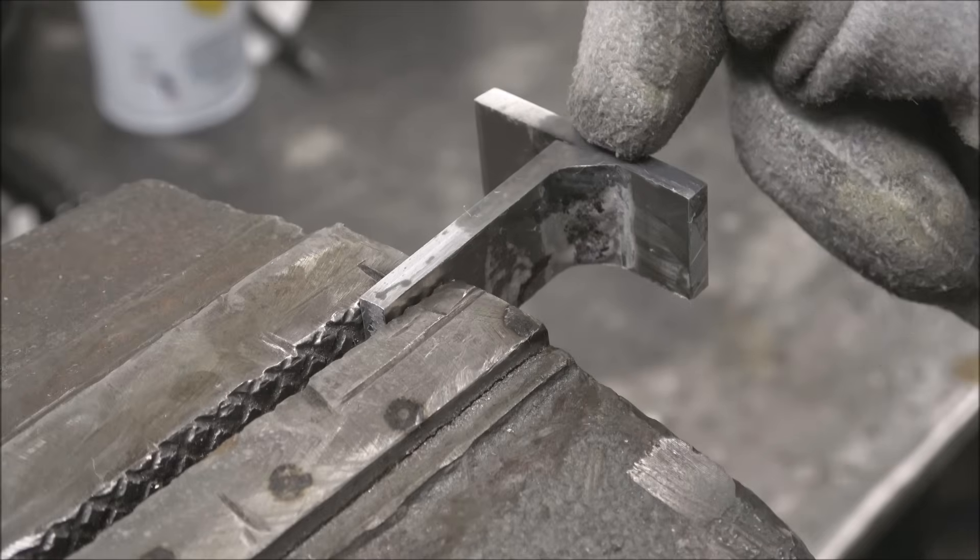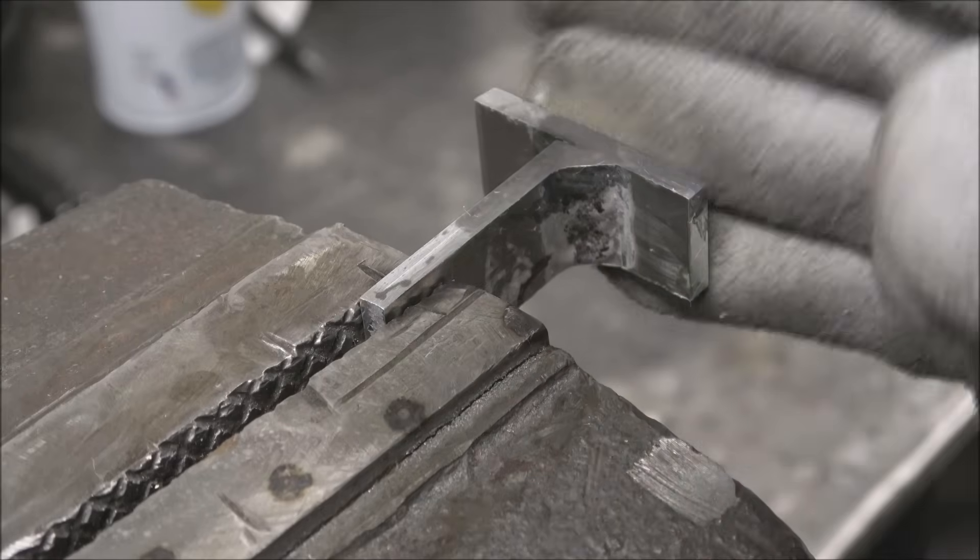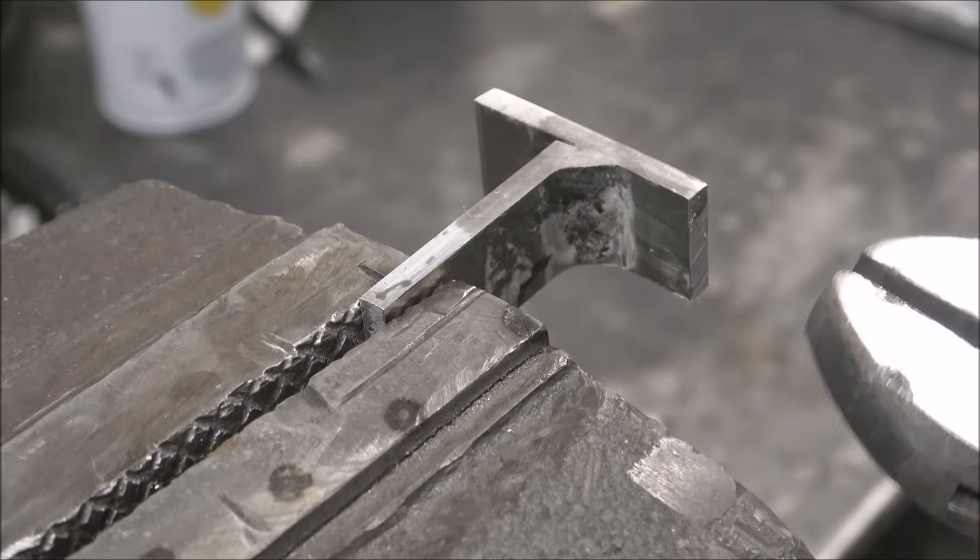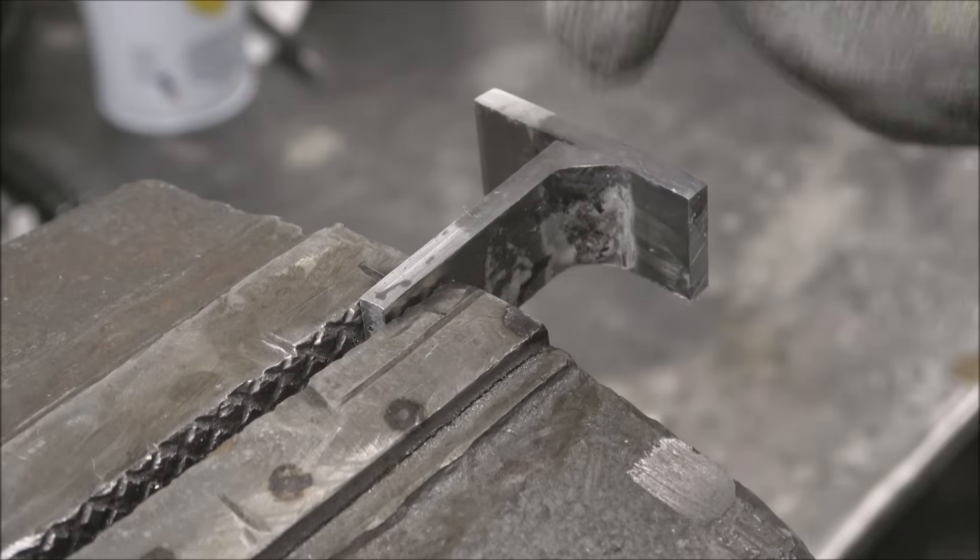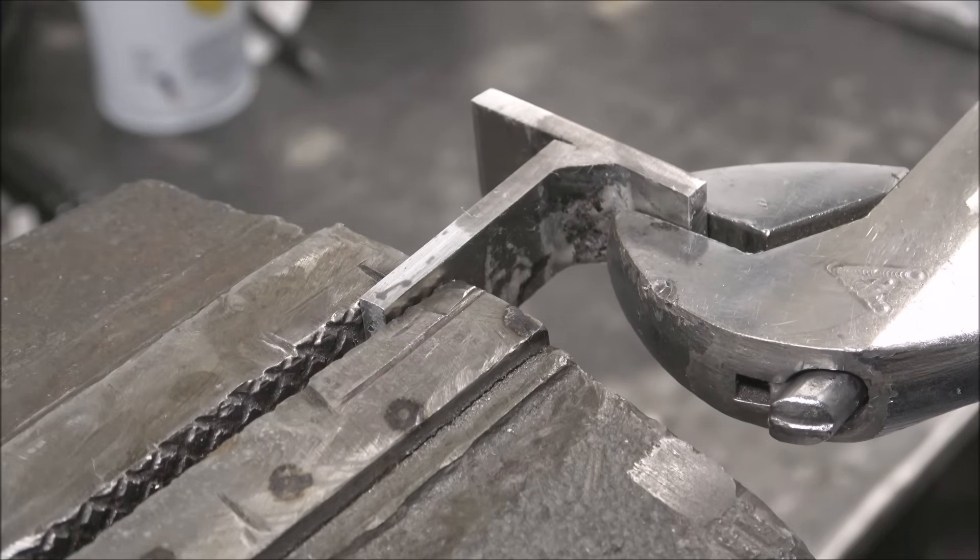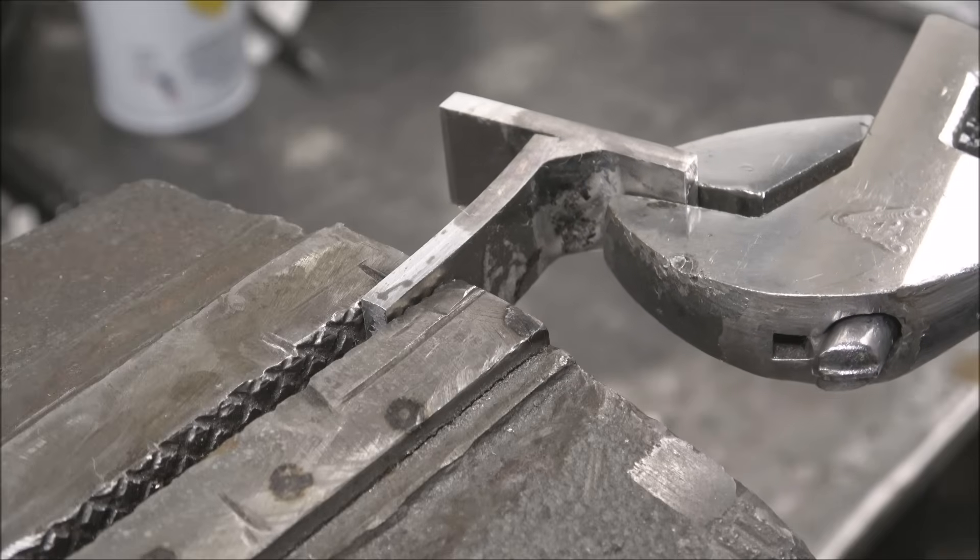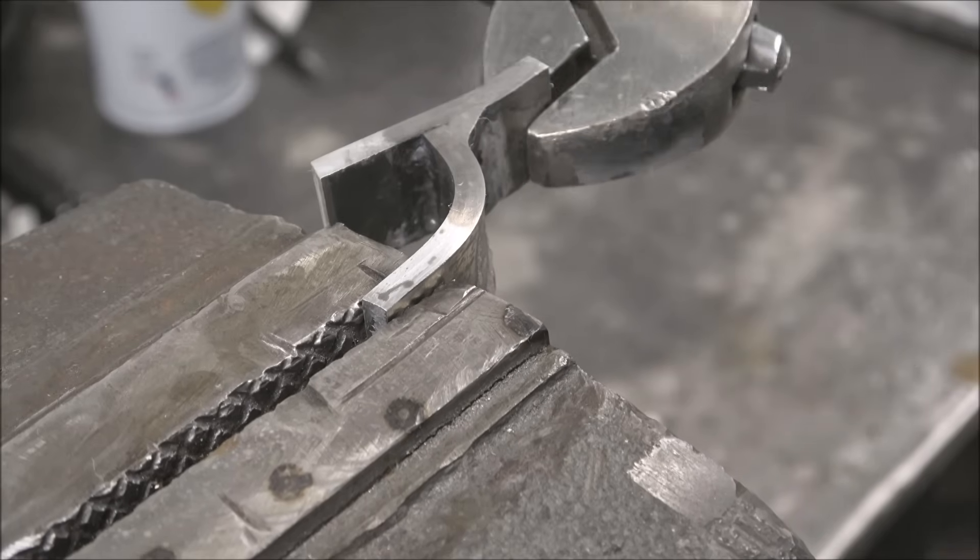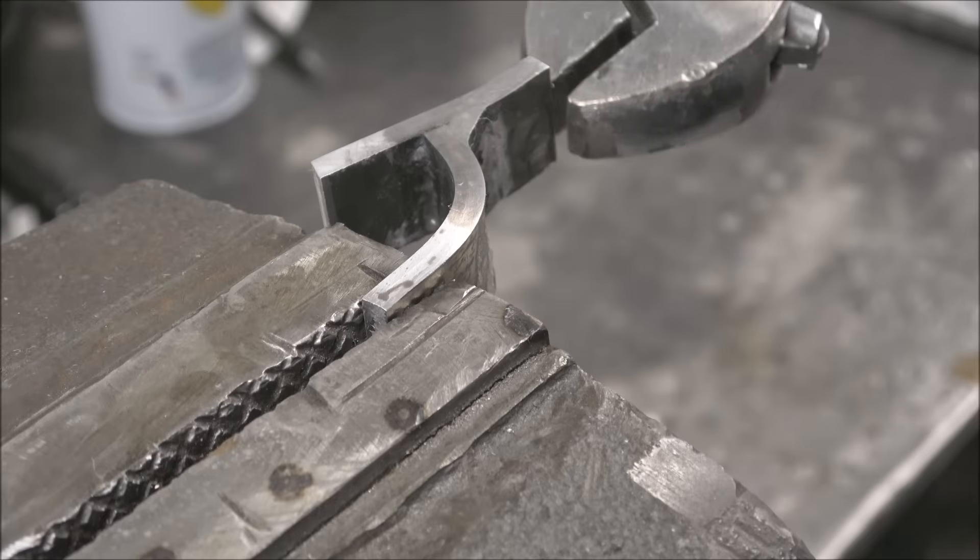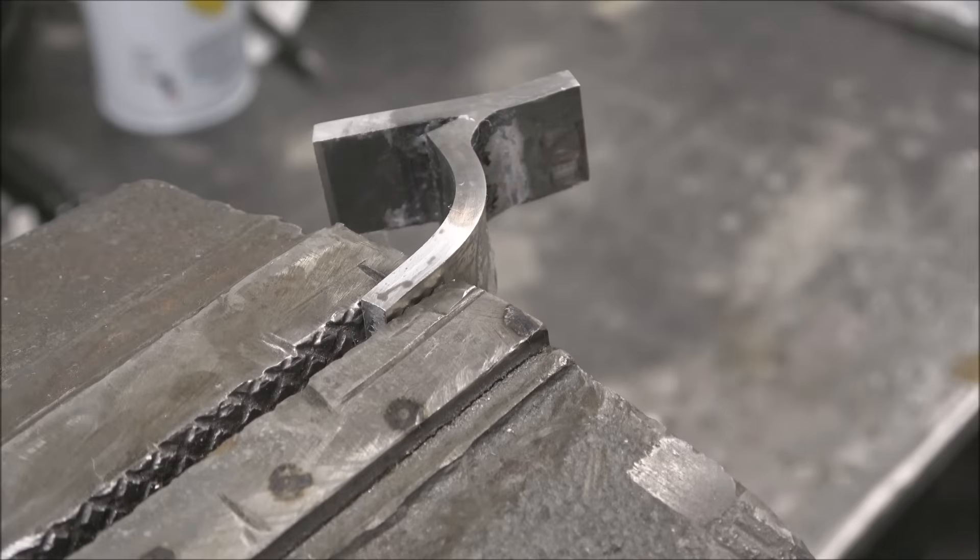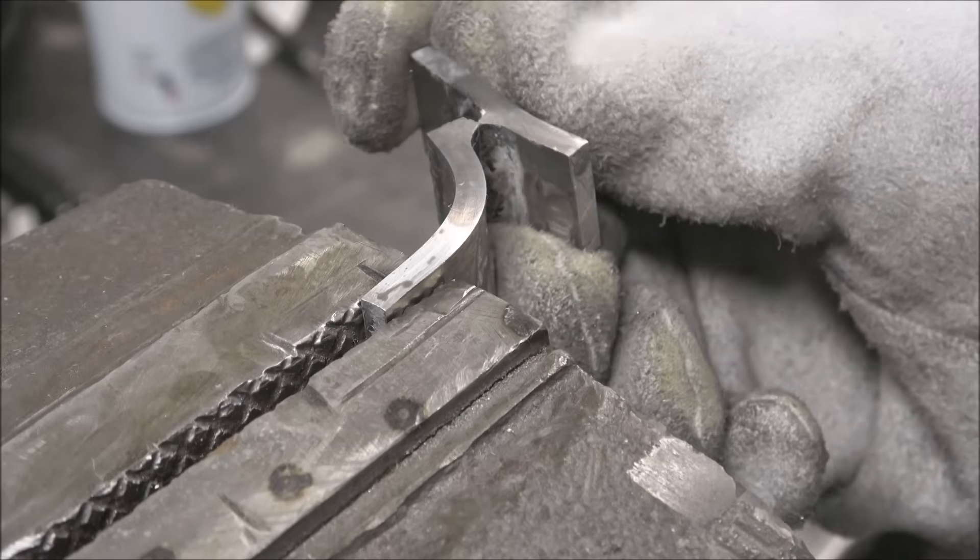Okay, so with that little crack in the middle going this way is going to make it crack easy. So I'm going to go this way first on this test just to see how good this rod bites in. Fuses. Okay, not too bad. Works a lot better than any other filler rod on 7075 that I've tried. But yeah, see right there I pulled back on it and that split super easy.